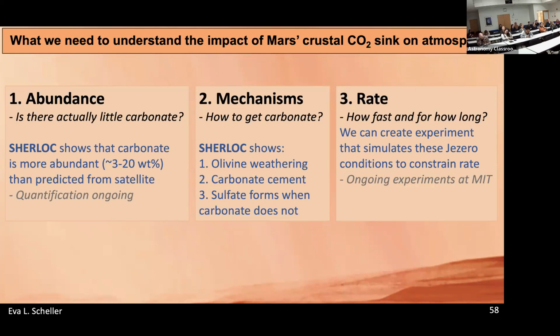Mechanistically, and this is to me the most important, we found and confirmed a way that carbonate forms on Mars, which is driven by olivine dissolution kinetics and olivine weathering. Before landing, we had all sorts of hypotheses for how the carbonate would form that I worked on for a long time. And so this was a great accomplishment that we could actually nail down that it is this olivine weathering process that is at work.